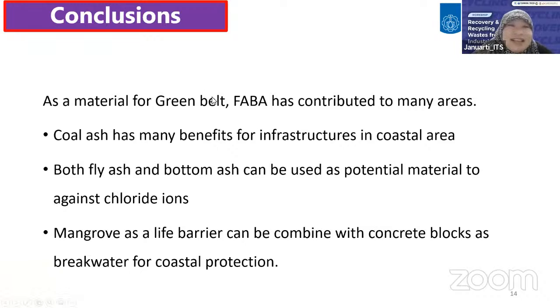As we can see here, for the green belt of the Indonesian coastline, fly ash and bottom ash have actually contributed to many areas. They have a lot of benefits for our infrastructures in coastal areas. Both fly ash and bottom ash can be used as a potential material to immobilize the chloride ion to protect our structure from corrosions. And again, mangrove as a living barrier can be combined with concrete blocks as a breakwater for coastal protection.